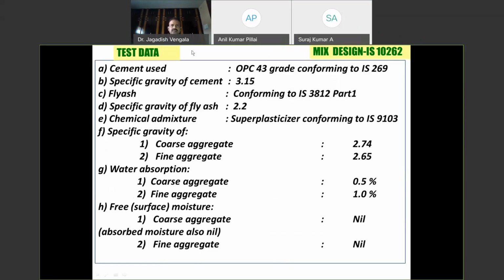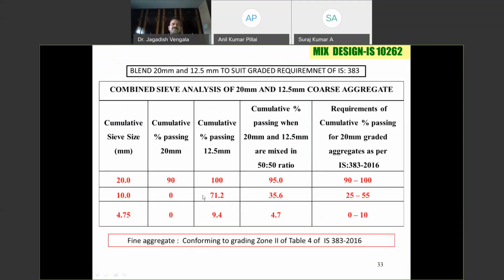And some of the properties, the test data: cement is OPC 43, specific gravity is 3.15. Fly ash is conforming to the IS 3812 requirement, specific gravity is around 2.2. Chemical admixture, plasticizer is used. And these are some of the properties of the coarse and fine aggregate. 2.7 is the coarse aggregate specific gravity, fine aggregate is 2.65, and water absorption in coarse aggregate is 0.5% and in fine aggregate is 1%. Moisture content is nil.